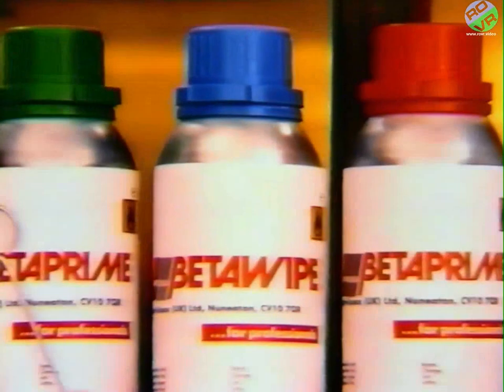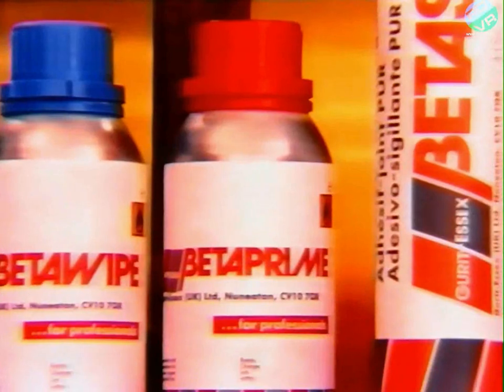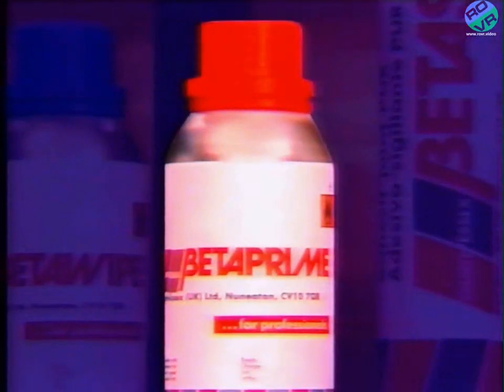BetaWipe 4000 urethane wipe is for the easy jobs where you've got a continuous layer of old urethane in place. BetaWipe 4000 has been specially designed for use on cutback urethane, encapsulated glass, and pre-applied sealant. BetaPrime 5402 body primer should be used when you've got an aperture without urethane, but with a sound coat of paint.